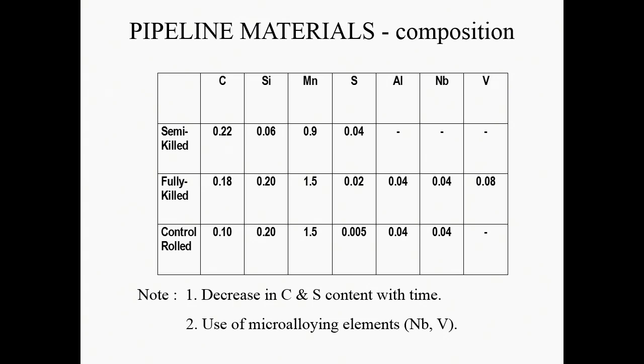Carbon content's come down. Well, we know carbon affects weldability, so that's good. Silicon content's gone up. That's because we've gone to a controlled rolled steel. Silicon does affect weldability, but at that percentage it's not a big effect. Manganese has gone up. That has an effect on weldability and strength as well. Sulfur, bad news, get rid of the sulfur. Yes, we can. So steels have much less sulfur in them nowadays, and that's one of the big sources of brittleness.